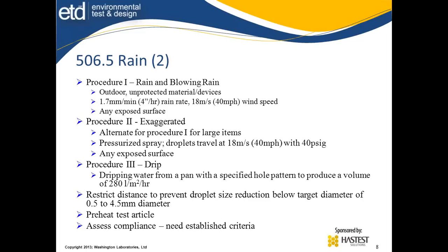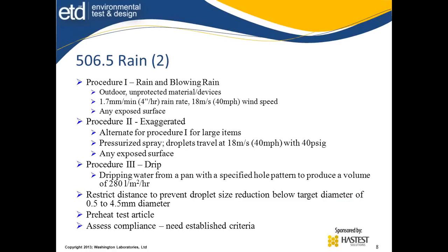Rain also calls for preheating of the test article for many occasions. If an item is preheated, it's out for solar exposure or just a hot item, you need to get it up to operating temperature or exposed temperatures, those that it can acquire from the environment. And that preheating will allow for the ingress because materials will now start cooling and you'll see the metals contract differently. Assess the compliance. You need to establish criteria because ingress could be allowed if it can tolerate it. So how much is too much? So a pass-fail criteria clearly needs to be determined for this test.